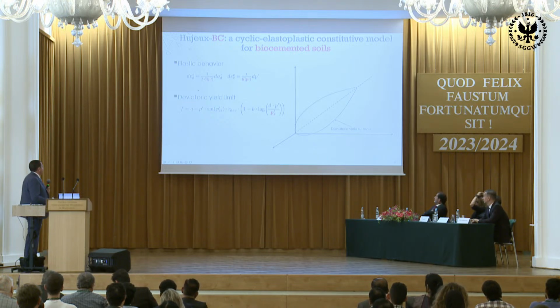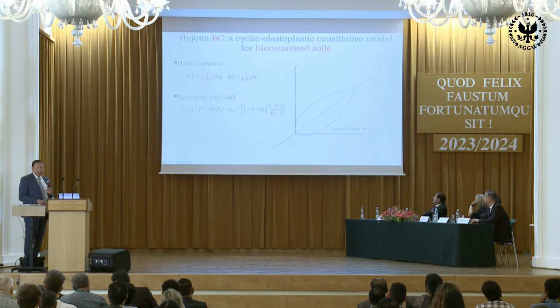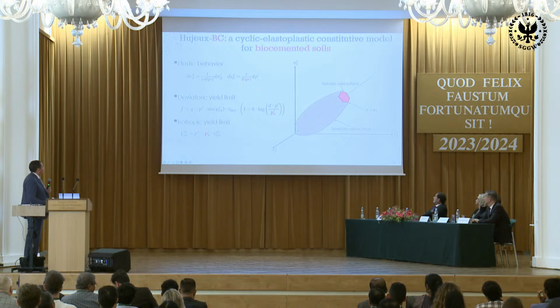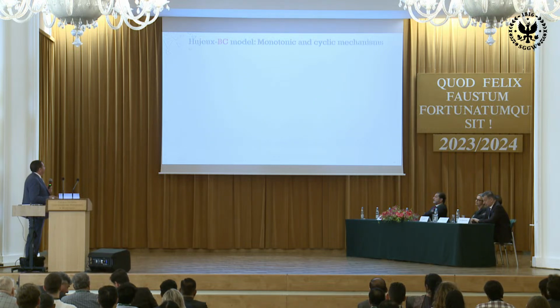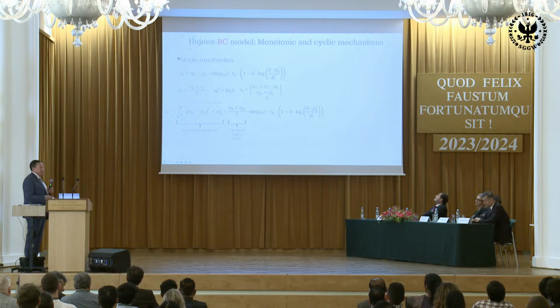It's an elastoplastic model. It has a yield limit that's very similar to Cam clay. For those who are familiar with Cam clay, there are just a few differences. So instead of the capital M, it's a sine here. And it has this shape, and because it has a fourth mechanism that cuts in the isotropic limit. So this is the elastic domain. It's a model like any other model. It's of interest for us because it has a cyclic mechanism in the behavior.